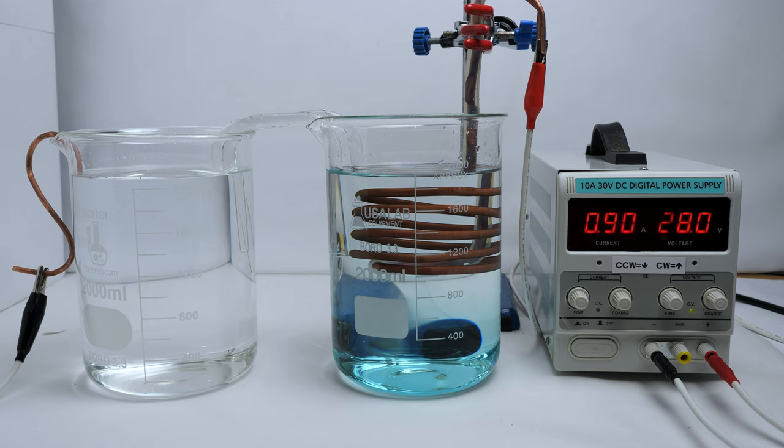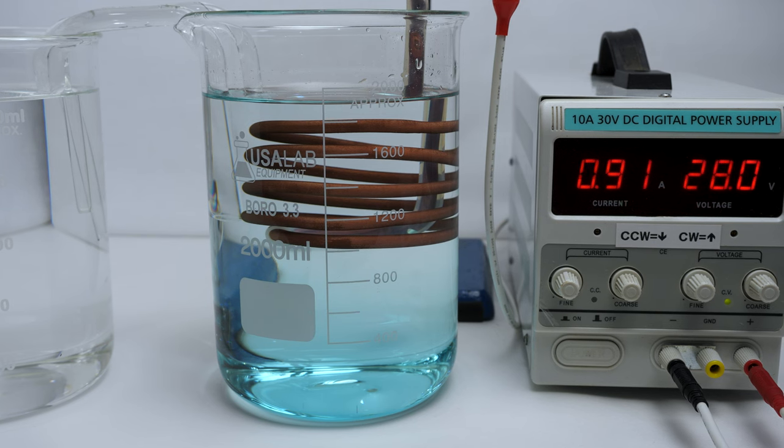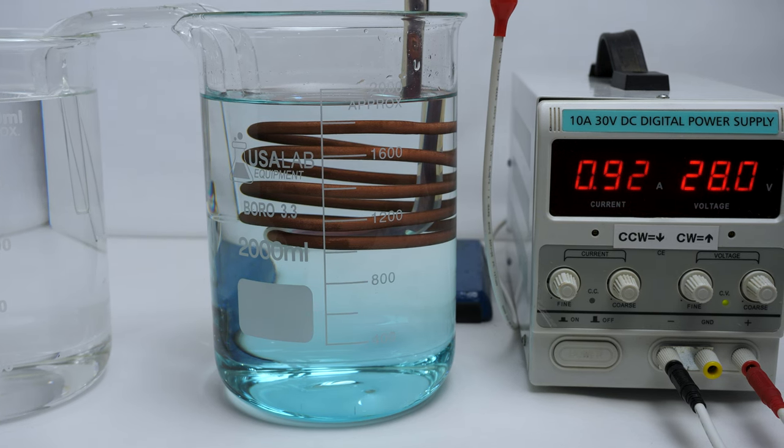Nothing comes for free, though. As a consequence to the electrodes being further apart and the small cross-section for conduction within the bridge, I dramatically reduce the current flow. Reduced current flow will result in decreased reaction speed. In an attempt to bolster the current, I added a second salt bridge, which doubled the cross-section, allowing for more electrolyte to carry the current. You can see I also increased the power supply's voltage quite a bit. The reaction will still proceed much slower than if the electrodes were closer together, but either way I'm in no particular rush, so no big deal.